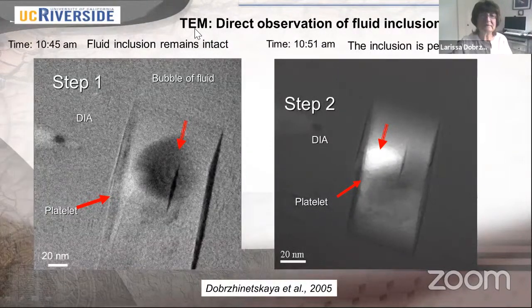at the microscope. We look at the inside of diamond and we found first this platelet. We know it's a structural defect of carbon atoms. Then we see suddenly this round material. Wow. And we looked at this round material. And finally, we see this round material started to move.